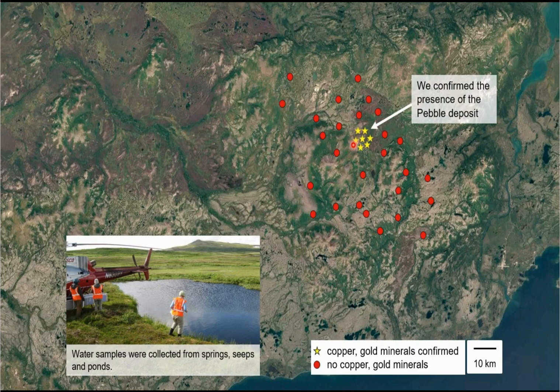All of the stars here, those are the water composition where waters were collected directly above the porphyry copper deposit, which sits beneath tens to more than 100 meters of exotic glacial till. So there's no sampling of the surface environment. There's no outcrop that would give you an indication of the presence of the Pebble deposit. The red, all of those are areas where we sampled waters, and their compositions isotopically tell us there's no copper